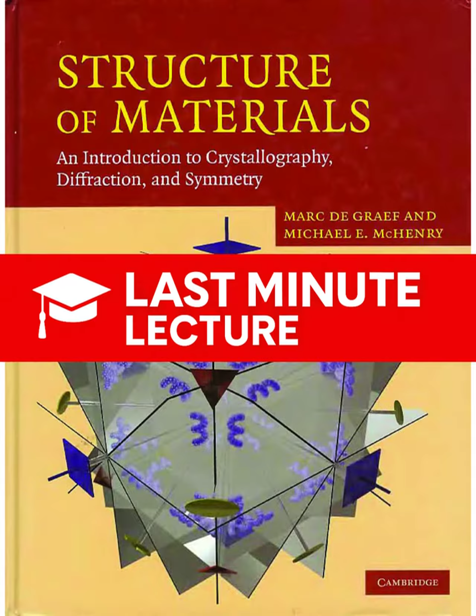And the geometric genius is this. The Bragg condition for diffraction is satisfied if and only if a reciprocal lattice point, G, falls precisely onto the surface of this Ewald sphere. So if a reciprocal lattice point touches the surface, boom, you get a reflection. You get a reflection. The vector connecting the center of the sphere, C, to that point, G, is the diffracted wave vector, k'. So this instantly solves the problem of orientation.